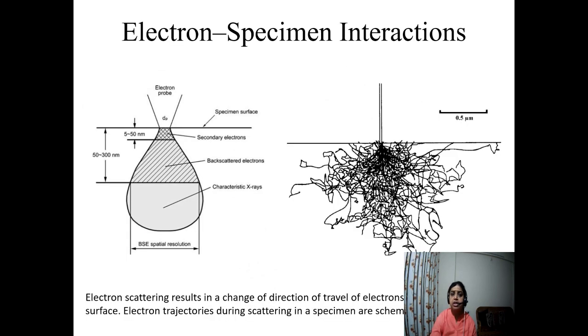Let's move ahead. Now let's come to the electron specimen interaction. Once the electron is inside the sample, it loses its energy. There can be different kinds of interaction, elastic and inelastic. In elastic interaction, it may scatter from the atom and produce a back scattered electron. For back scattered electrons, you can see the top 300 nanometer here gives compositional contrast. And the top 50 nanometer is the volume from where the secondary electron comes, because it is coming from inside the atom itself, not scattering from the atom. That is why it is used for topographical contrast.